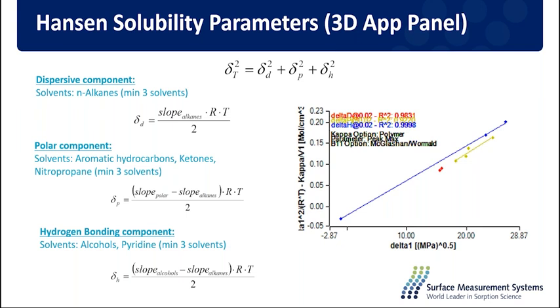The Hansen solubility parameter set contains three components. The first is the dispersive contribution of the solubility parameter. The second is the polar, and the last is the hydrogen bonding part of the solubility parameter. And these three components give the total solubility parameter, the total Hansen solubility parameter. To determine this with the IGC system, you need to use different types of solvents in order to measure the different interactions on the surface.